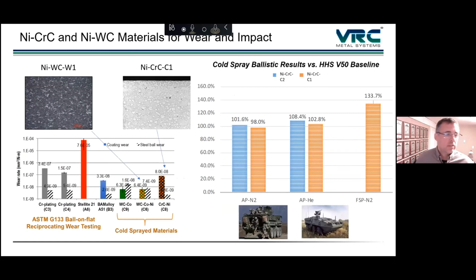This is showing some wear and impact resistance materials. So we're stepping away from aluminum and starting to look at nickel with tungsten carbide or nickel with chrome carbide. And you can see dramatic improvements in wear performance over chrome plating in the bottom left. And then on the right, you can see for the chrome carbide nickel, you can see an actual improvement in